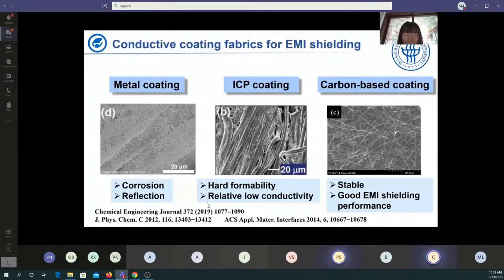Another one for the coating is intrinsic conductive polymers. Because of the polymer, it is hard to fabricate only by the polymer, and the conductivity of the fabric is relatively low. And with the rapid development of graphene, carbon black, and carbon nanotubes, carbon-based coating has emerged as a promising candidate for EMI shielding fabrics. This kind of coating is stable and always exhibits good EMI shielding performance.